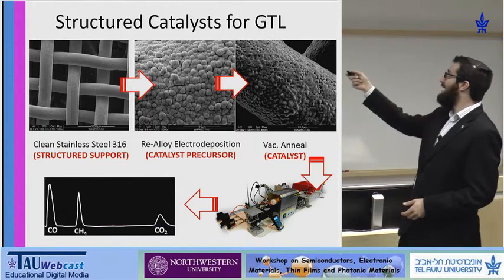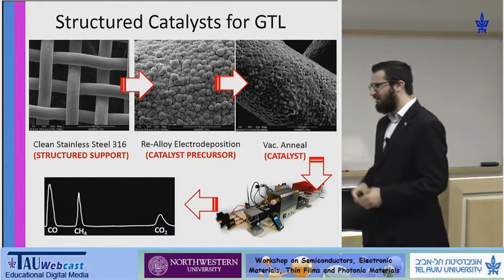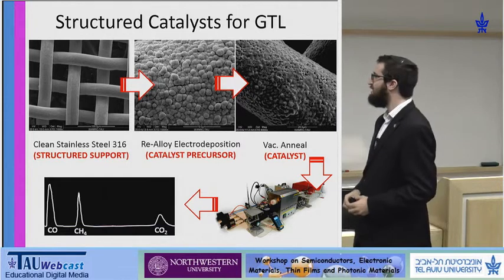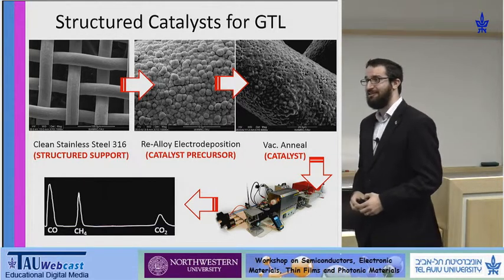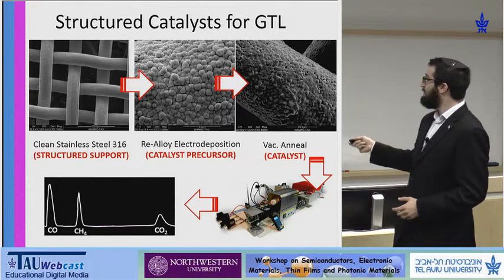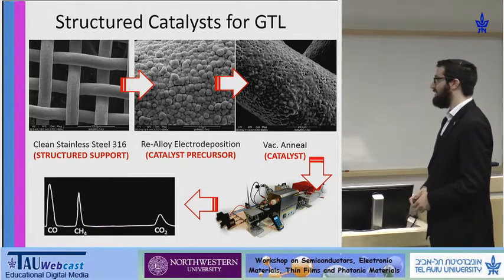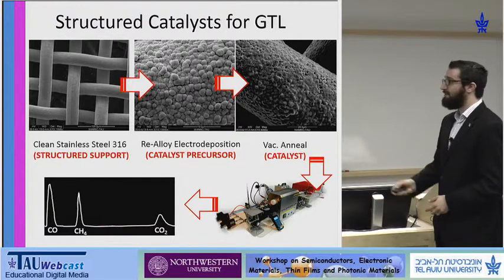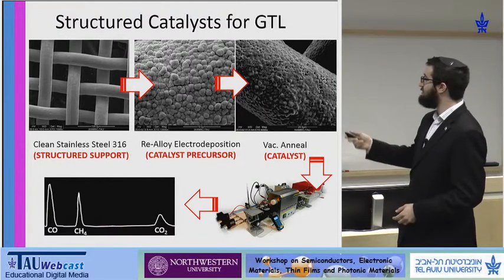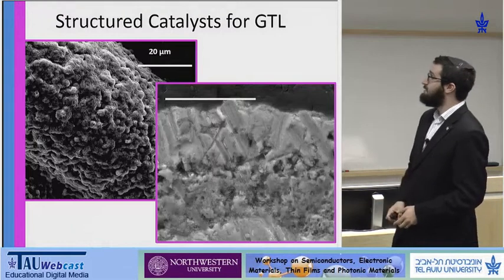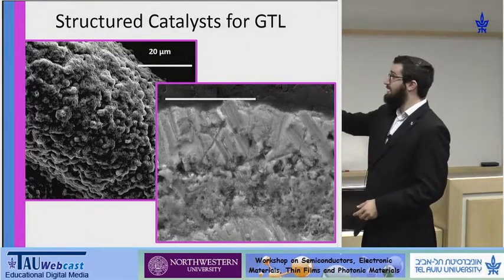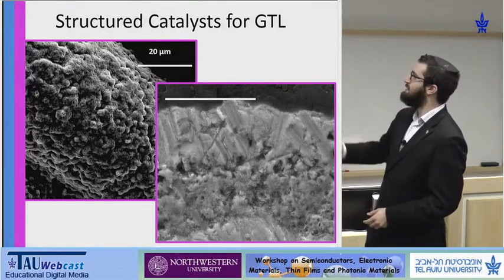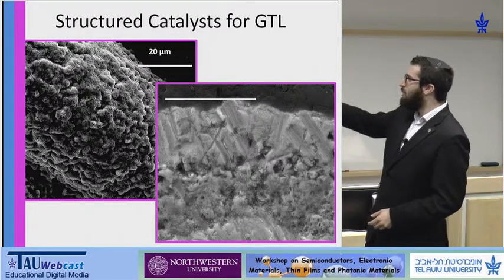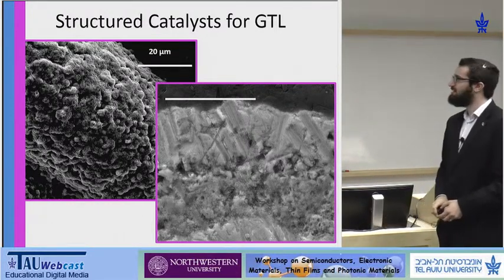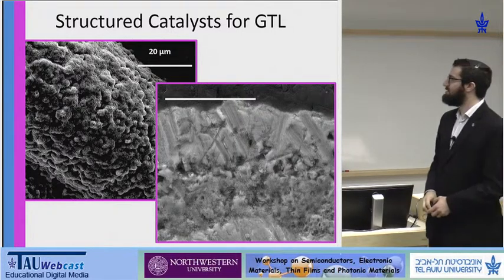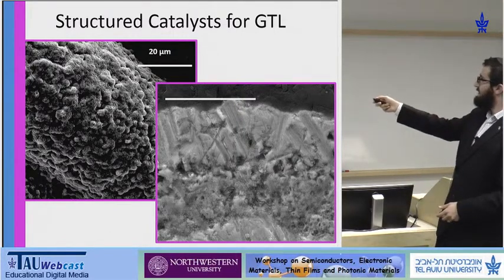Also, the fact that it's a rhenium alloy metal foam, or a metal sponge, if you will, it's quite a novel material that we're very interested in measuring. And what we do is we put it inside of our reaction chamber, and we're measuring for methane and carbon dioxide conversion using gas chromatography. So this is the cross-section of that same material. This is the top-down version of that same material. We see this very porous, foamy metal structure that we've put on top of the stainless steel fibers, which is very nice.